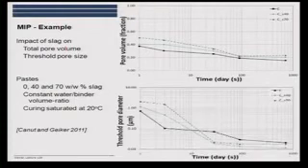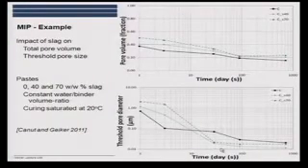But when we look at the threshold pore diameter, you can see that the slag has this impact. It refines the pore structure. At early age, we have the coarse threshold pore sizes, but then already around 28 days, the slag provides more resistance to ingress. We have these threshold pores becoming smaller and smaller. So a refinement of the structure. And that's what you also see from other data.